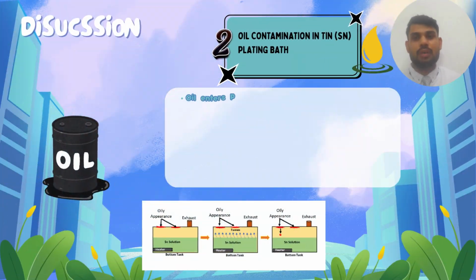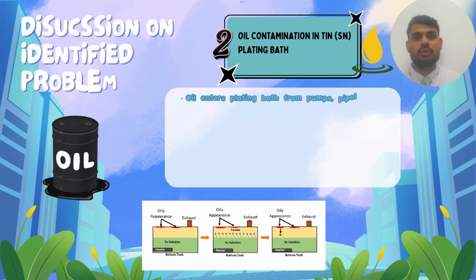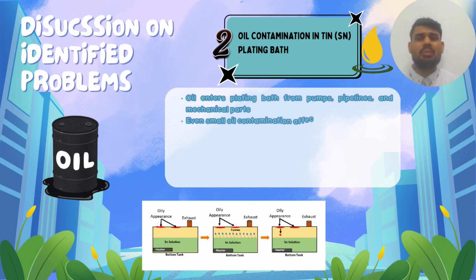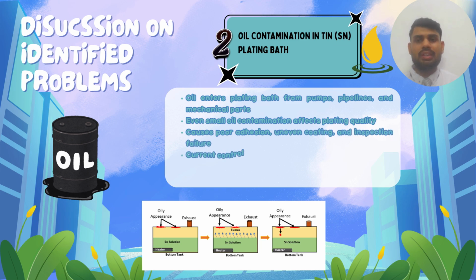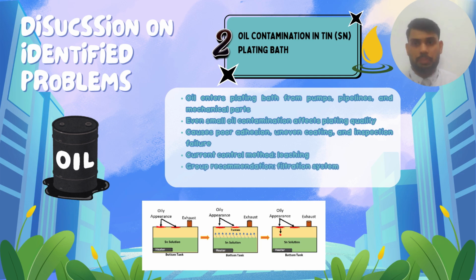Thank you, Farisha. So I'm going to talk about the second problem, which is oil contamination in the tin plating bath. So one major technical issue in the plating industry is contamination in the tin plating bath. Oil can enter the bath from mechanical components such as pumps, pipelines, and moving parts during continuous operation. Even a very small amount of oil is enough to affect the plating solution.